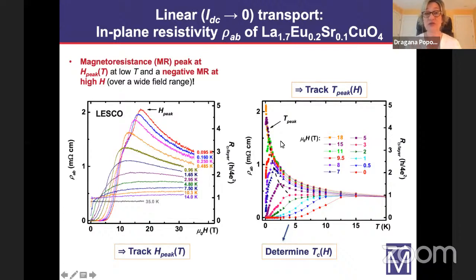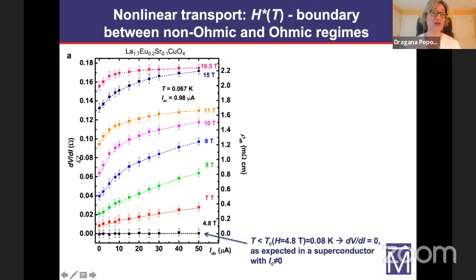So in addition to this linear transport, as I said, we measured nonlinear transport, in particular differential resistance as a function of the applied DC current. So here are the results shown for one fixed low temperature for different magnetic fields. The bottom trace corresponds to the case when we are below TC. We are in the vortex solid, and this is why we are measuring zero resistance, and the applied current is still below the critical current. So this is what's expected.